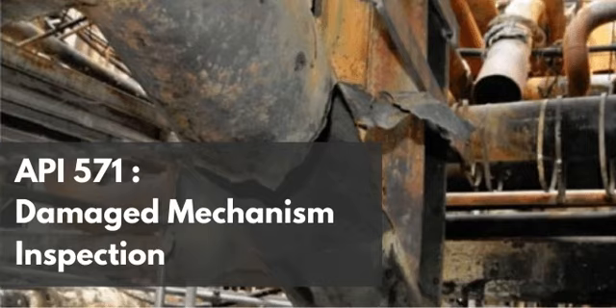Exactly. For decades, the residual stress from the original 1970s construction welds sat there completely dormant because the pH was maybe 7.5 or because there was no free liquid water. But then one small change pushes it over the edge. Right. The moment the operational creep pushed the local environment over that pH 8.0 threshold and a liquid film condensed, the chemical catalyst was initiated. The surface film broke down, and the pent-up mechanical energy from 52 years ago finally had the avenue to rip the grain boundaries apart. That is just wild to think about.